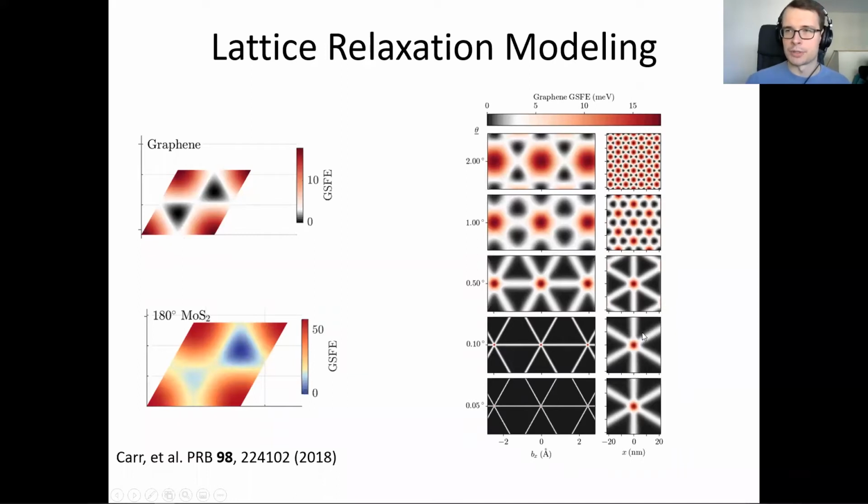And this is a pretty standard result from any sort of elasticity theory with a twisted boundary condition or some sort of topological defect. There's going to be some lowest energy mode, some lowest amount of curvature that you can introduce to the material. Whereas if you tried to make this node any smaller or made the wall any thinner, the additional curvature energy would beat the gain you would get in the interlayer energy. But the key takeaway is that at very small angles, we see examples that are very similar to the experiment and that are well described by this continuum theory. Large triangles of uniform stacking separated by thin walls of these soliton solutions of the PDE.